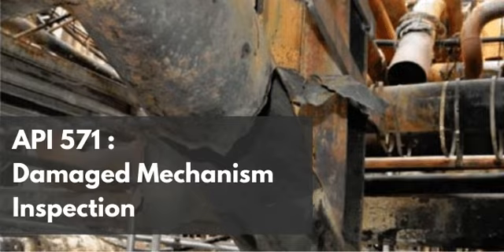Phase transitions. Exactly. When you're absorbing gas, or more importantly, when you're stripping the gas out of the rich amine, the fluid is extremely turbulent. You have flashing, boiling, and the rapid desorption of H2S and CO2. What does that turbulence do to our protective scale? This dynamic chemical shifting, combined with the thermal and mechanical turbulence, destabilizes and literally strips away that protective iron sulfide scale. So the barrier is constantly being broken down and rebuilt. Exactly. And during the periods where the FeS scale is stripped away, the highly stressed carbon steel is suddenly exposed to a fluid that is rapidly becoming lean and aggressive. Because the gas is leaving it. Right. And that transient exposure is all the mechanism needs to initiate a crack.